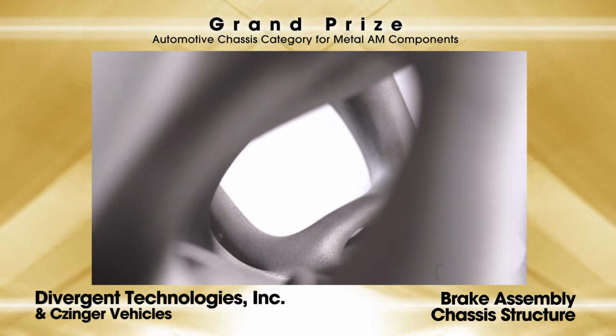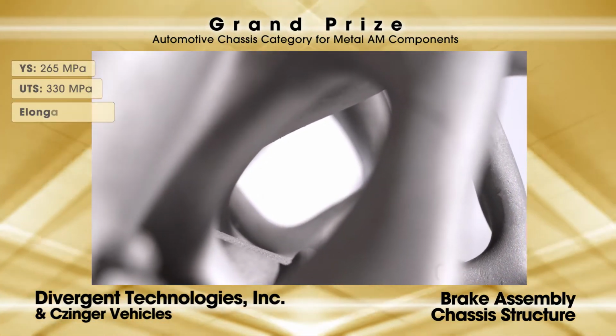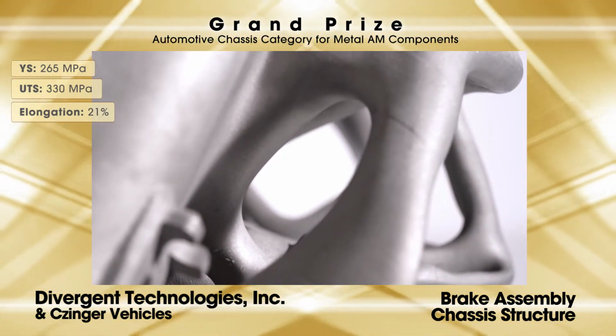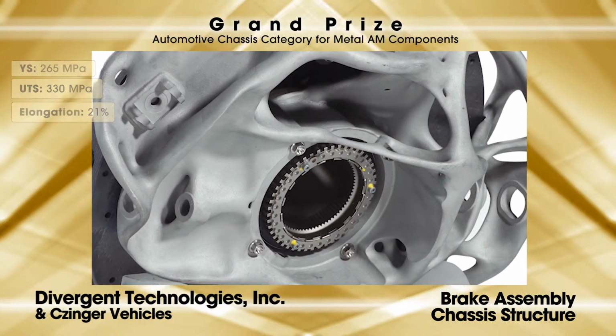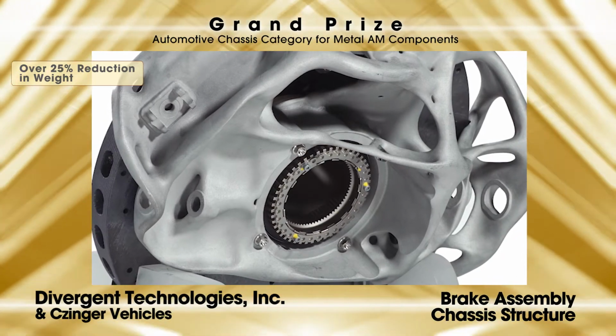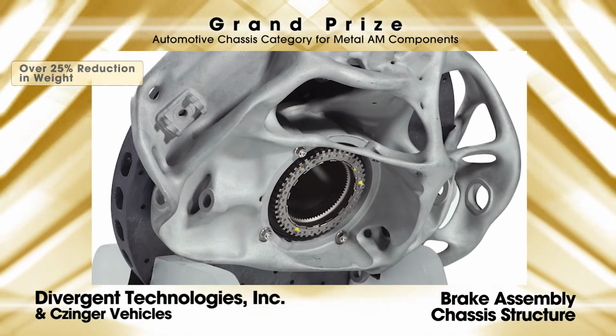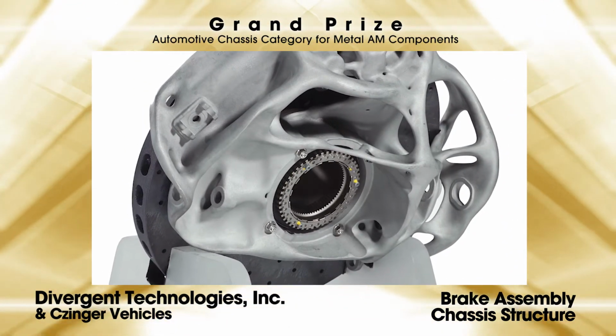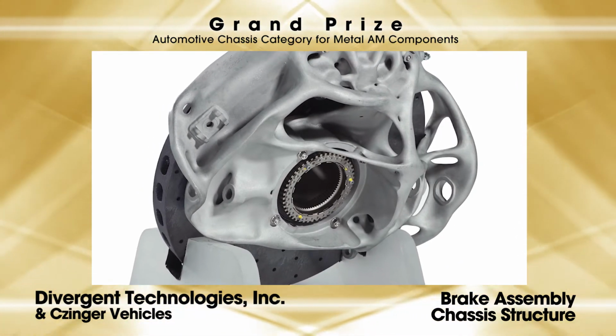Using a proprietary high-performance aluminum alloy, the material has a yield strength of 265 megapascals, an ultimate tensile strength of 330 megapascals, and an elongation of 21%. The mass has been reduced by over 25% from many of the components that were already designed for higher-end, lightweight vehicles. Full vehicle validation was completed and the component passed accelerated durability and proving ground abuse, dynamic stiffness, noise vibration harshness, as well as various federal motor vehicle safety standards.